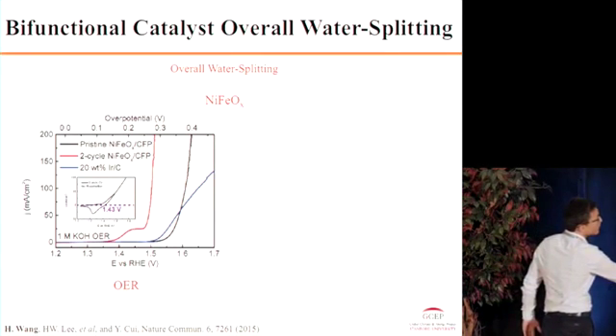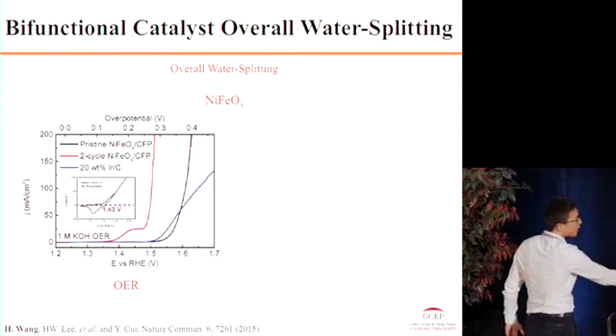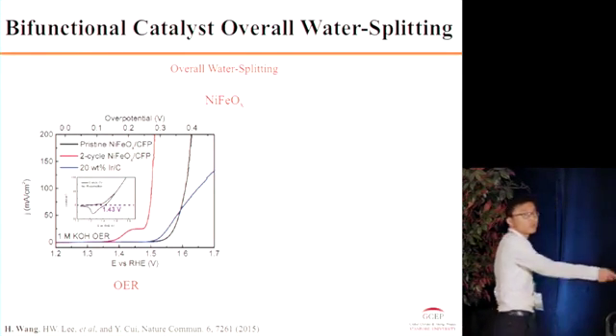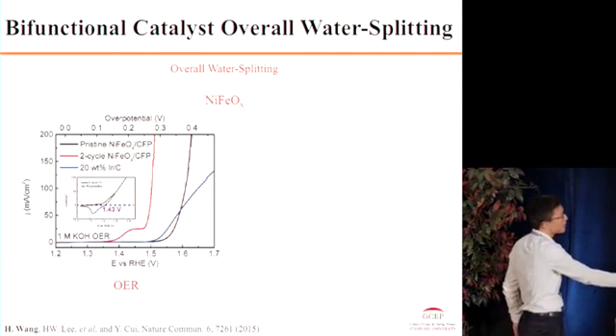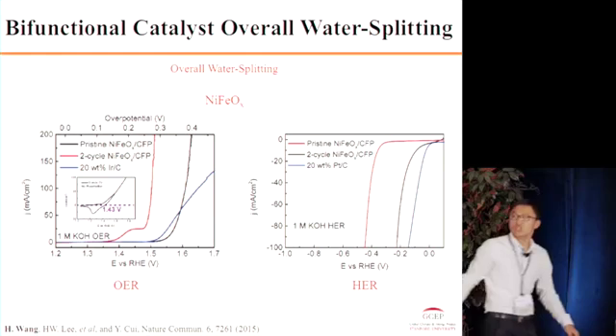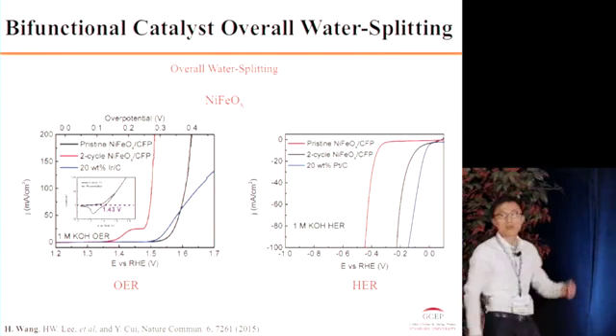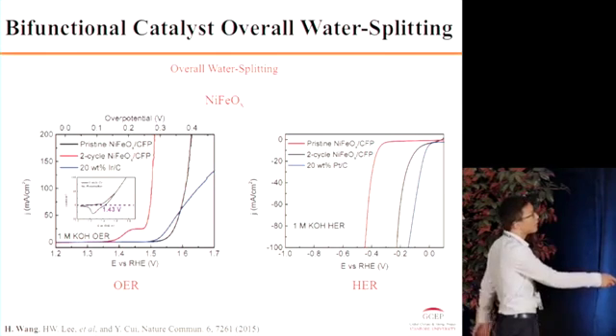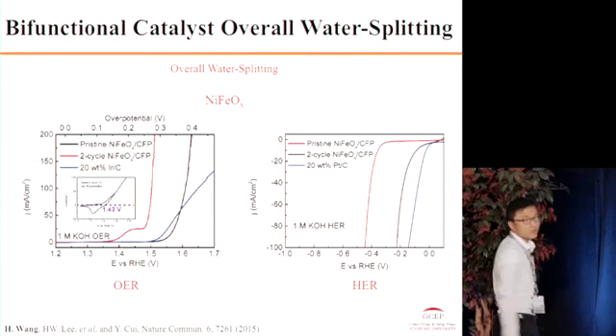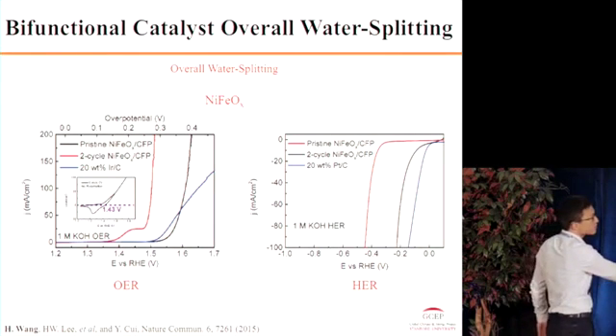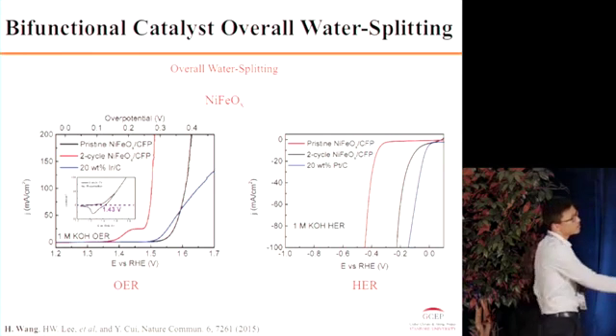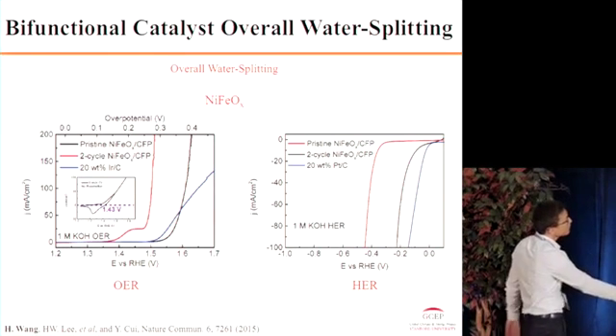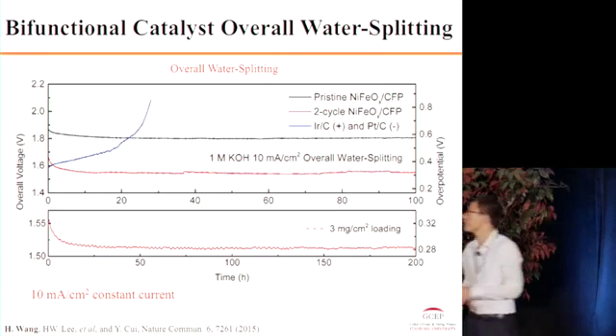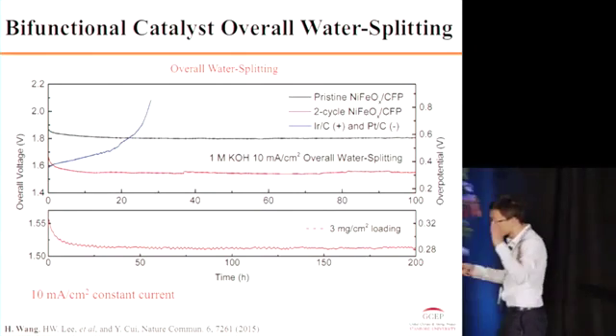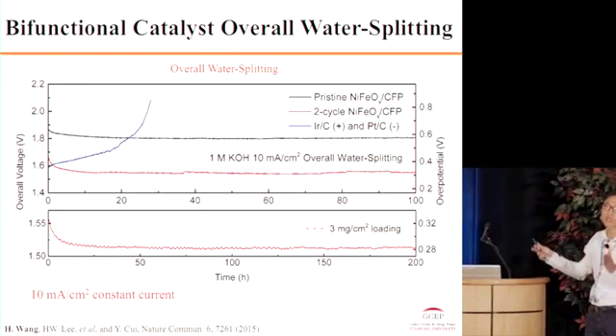As we can see, the blue curve is the benchmark iridium carbon. And after tuning, the performance of the OER is much better than the iridium. And interestingly, we also realized that the hydrogen evolution reaction for the same material, nickel iron oxide, after tuning, is also significantly improved. As we can see, the pristine has more than 300 millivolts overpotential, but it shifts to 100 millivolts overpotential, which goes very close to platinum. So we can successfully combine these two catalysts, the same catalyst, together to drive the full water splitting reaction.